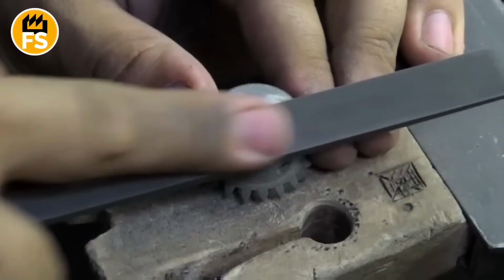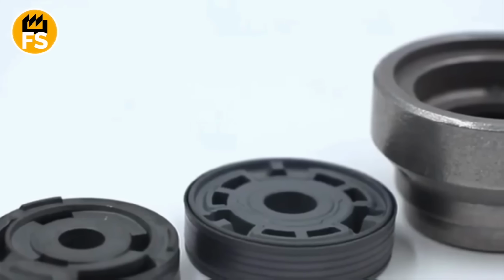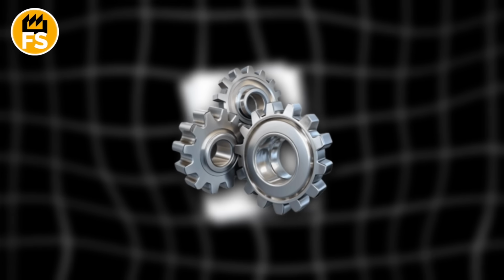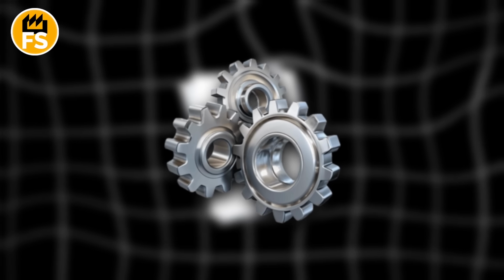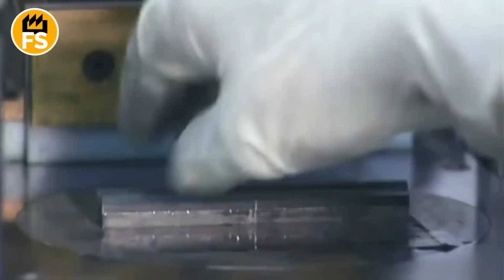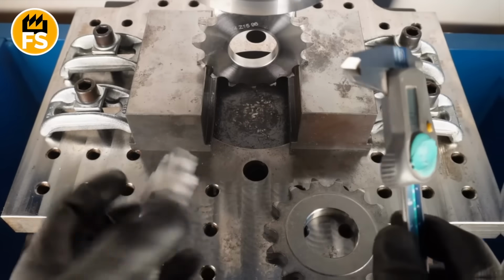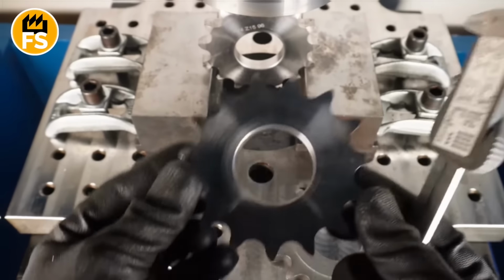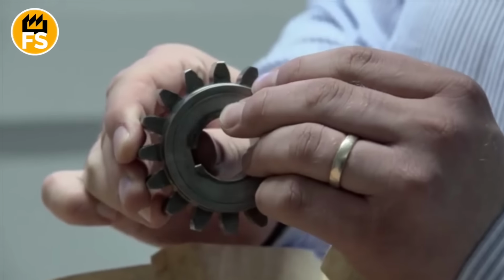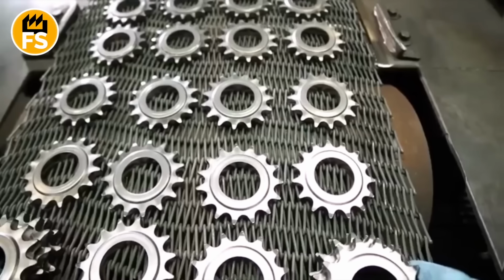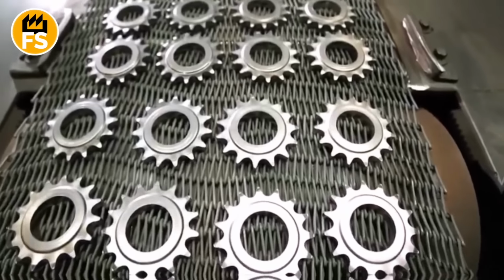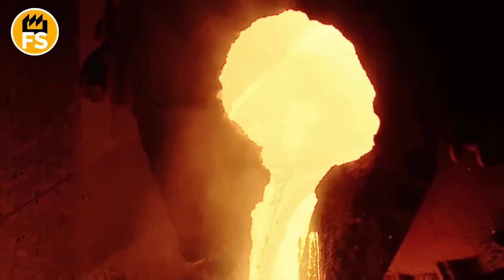Dimensions hold to within a few hundredths of a millimeter. For comparison, a sheet of paper is about 100 micrometers thick, and powder part precision can be 10 times better. You can create gradient materials, where different parts of a single component have different compositions and properties. For example, a gear where the teeth are made from hard, wear-resistant alloy, while the core is made from softer, tougher metal that won't break under load. You can't do this with casting or machining.